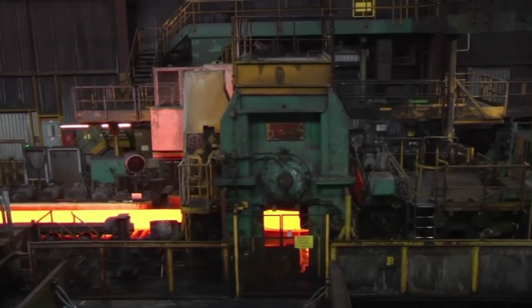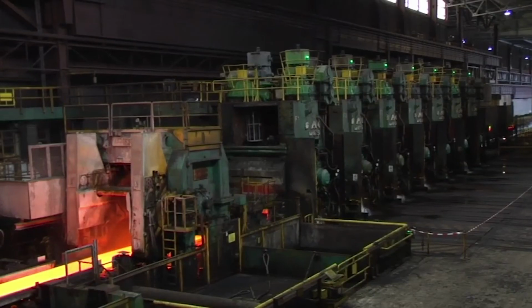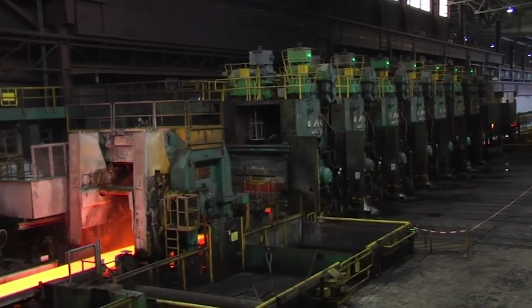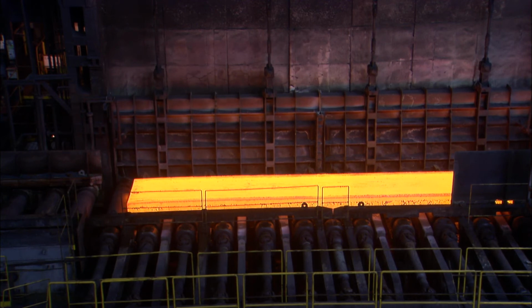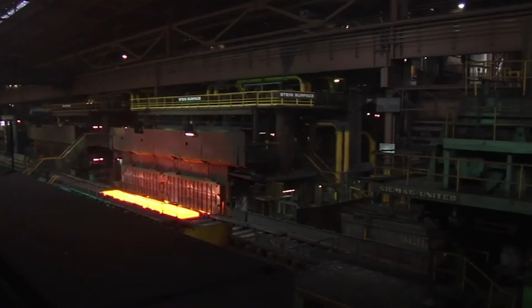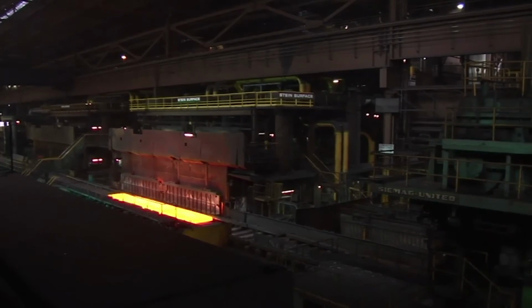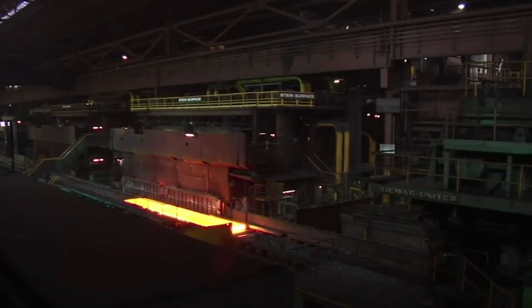ArcelorMittal Bremen has a very powerful roughing and finishing mill, capable to thermomechanically roll large cross sections. During this process, the rolling is done below recrystallization temperature, where we have accumulation of deformation, and this imposes higher rolling forces in the finishing mill especially. By adding niobium, we increase recrystallization temperature and have relaxation of the temperature constraint in our finishing mill. We don't have high mill loads, and we get desired properties much easier.